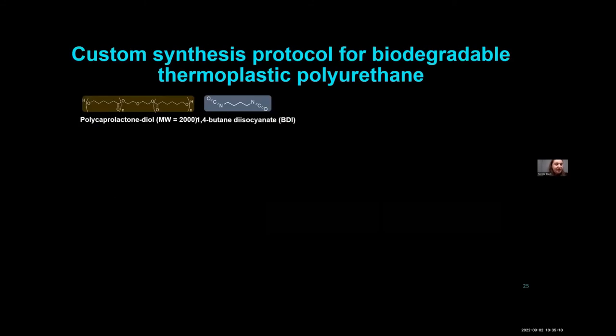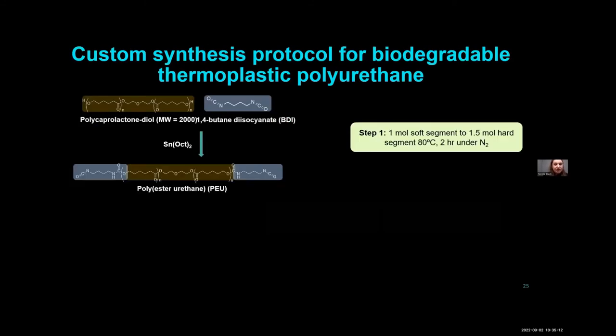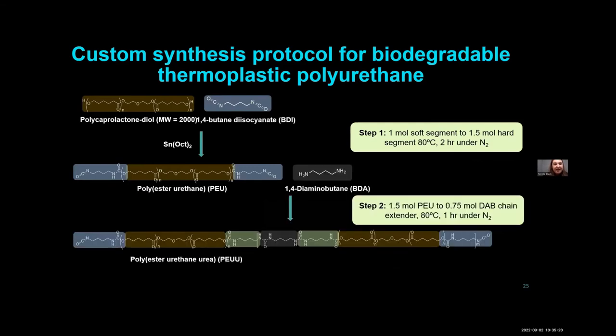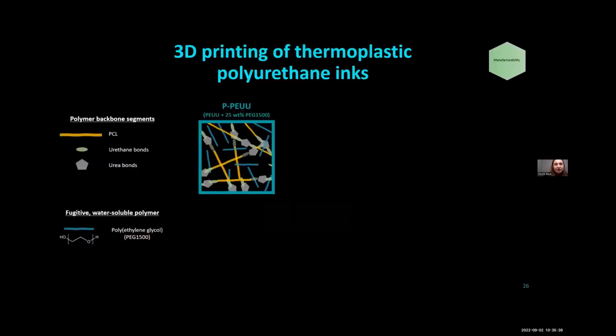So we essentially innovated this new material system whereby we reacted these PCL diols with these degradable ester groups with a diisocyanate, forming these polyester urethanes. We can then combine those with a chain extender called diaminobutane and essentially lengthen the chains on these. And what we end up with at the end of the day is a polyester urethane urea material, which can be extruded under high temperatures.